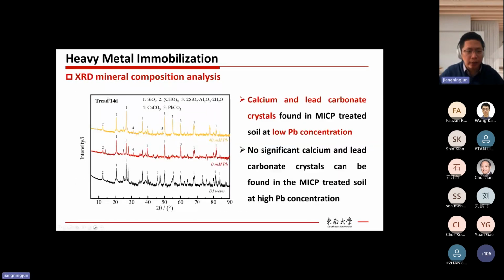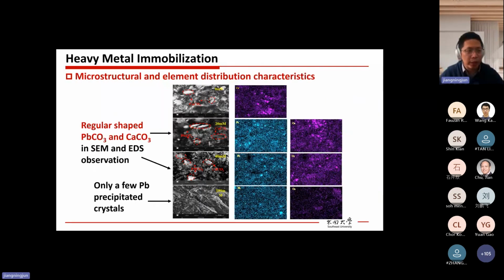Then the XRD analysis could help us to reveal what is present in the soil after MICP treatment. As we can see, for this case, with 40 millimole lead, we can see both calcium carbonate and lead carbonate. We can see both of them. However, for even higher lead concentration cases, I didn't put it here, but for that case, we could not find any calcium or lead carbonate. It means that the reaction has been retarded. Then combined with the SEM results, we can further understand it.